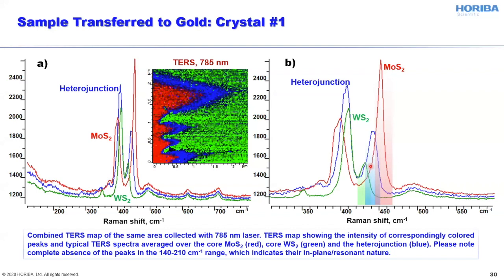And the fact that we have the low wave number, low energy peaks disappearing in case of non-resonant excitation may be a direct indication that all these modes are in-plane modes, that we are not observing with non-resonant excitation, which is sensitive only to the out-of-plane modes.